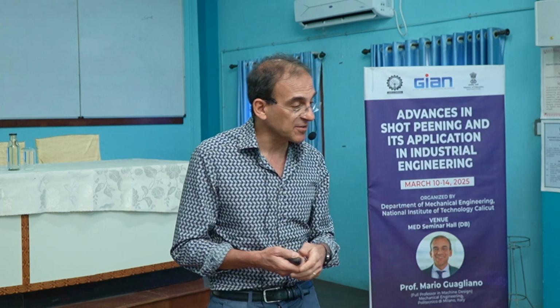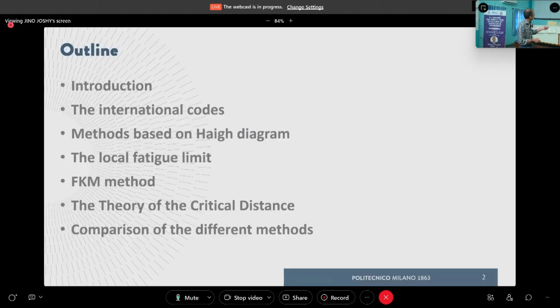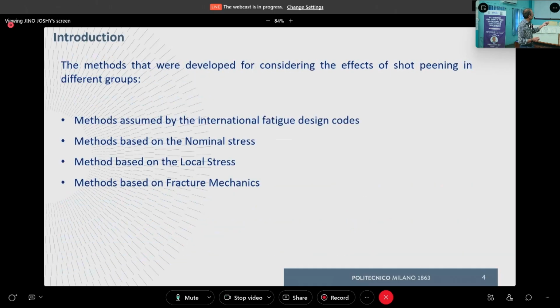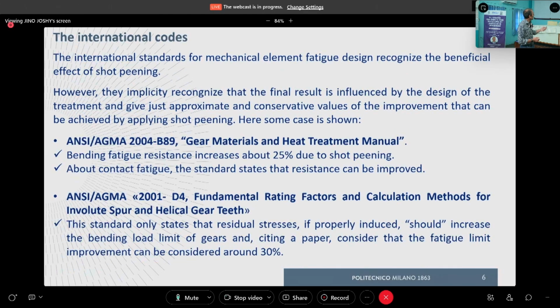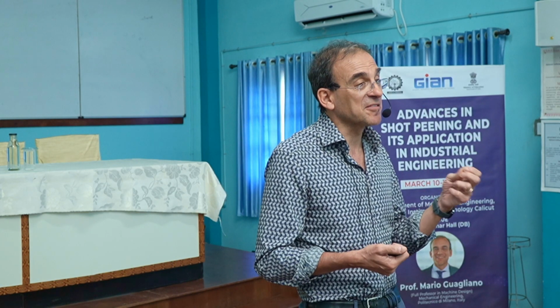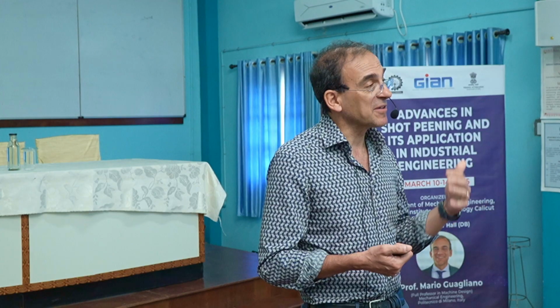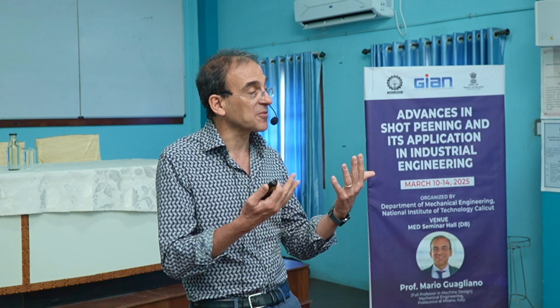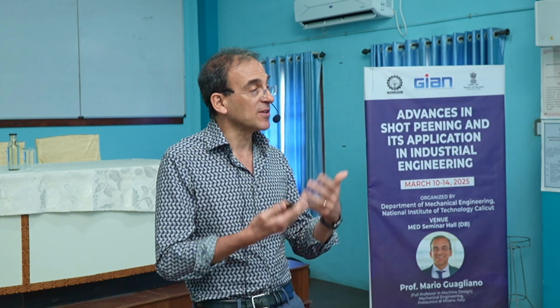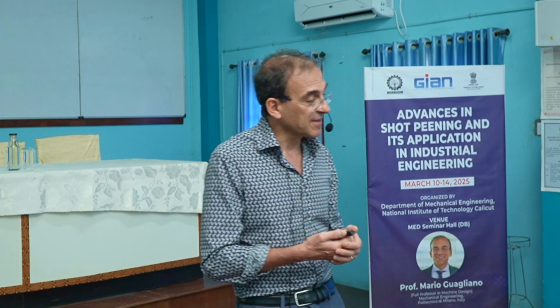But if we consider contact fatigue, the AGMA standard says that resistance can be improved. This is maybe a bit disappointing. Let's say that we could hope for something more than this. But also in this case, contact fatigue is an even more complicated subject with respect to bending fatigue, because the same problem of fatigue remains, but also the influence of the contact condition, lubrication and so on plays a role, and so it's even more complicated.